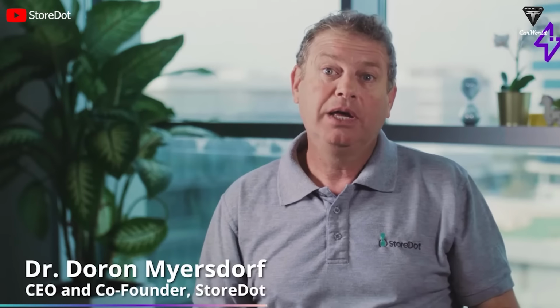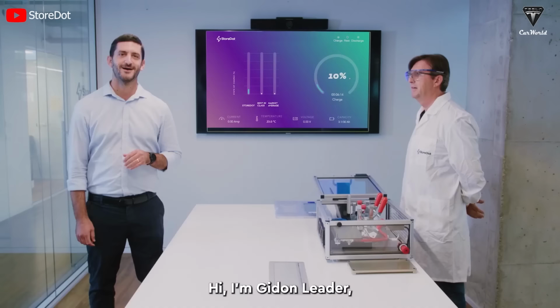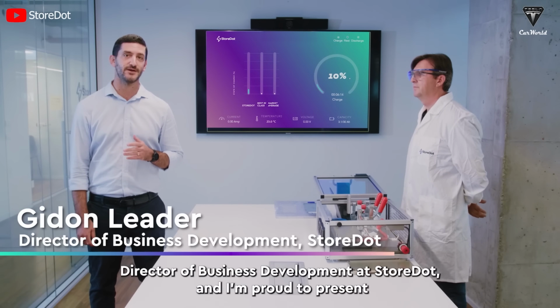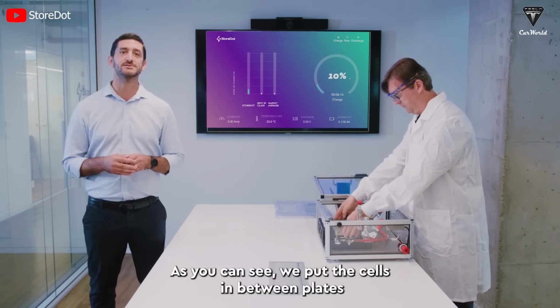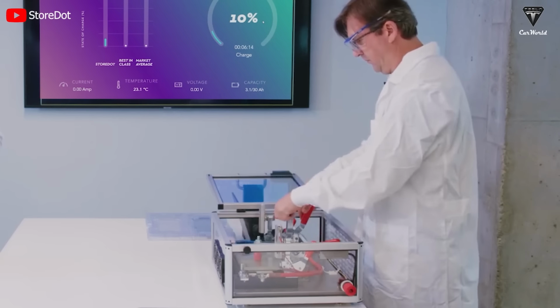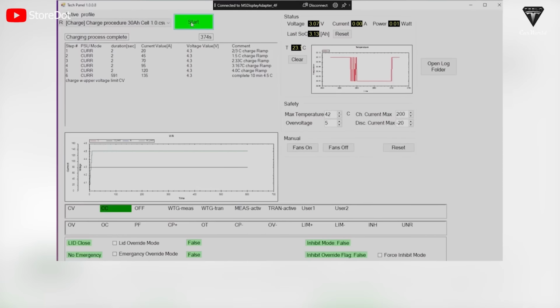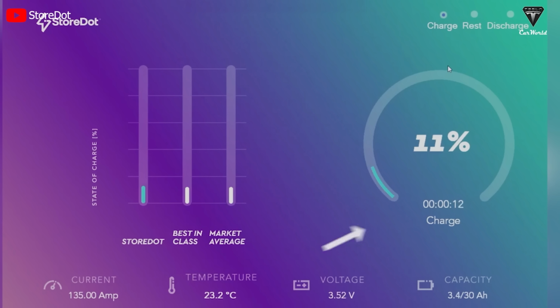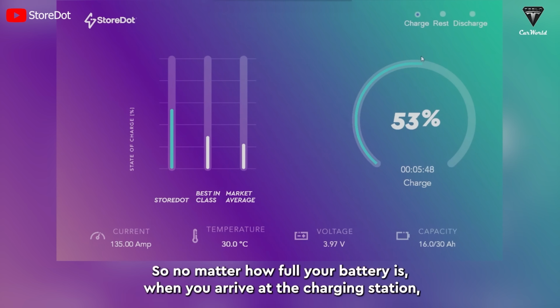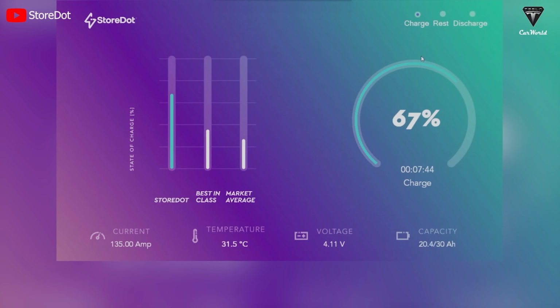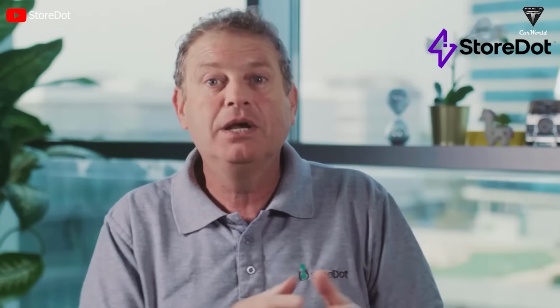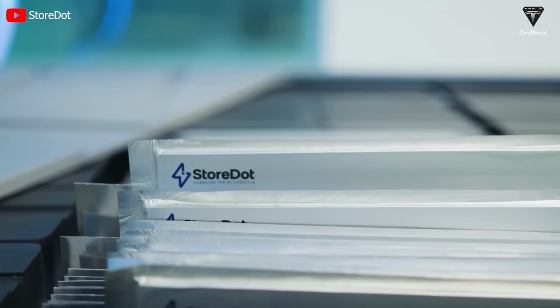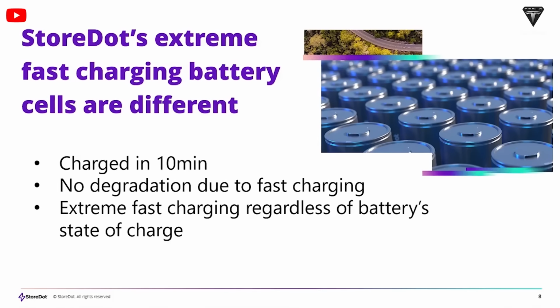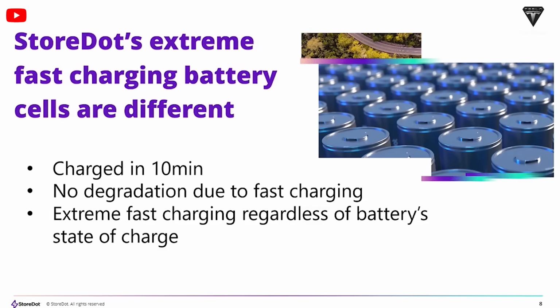In early November, we received information that StoreDot conducted an experiment involving multiple consecutive fast charging cycles and compared them with slow charging scenarios. Specifically, the company carried out 1,000 consecutive fast charging XFC tests, including sessions where the state of charge increased from 10 to 80% in just 10 minutes, as well as charging the state of charge, SOC, from 0 to 100% using extreme fast charging. After the experiments, StoreDot achieved an impressive result: the XFC cells did not experience degradation compared to cells charged slowly from 0 to 100% SOC.